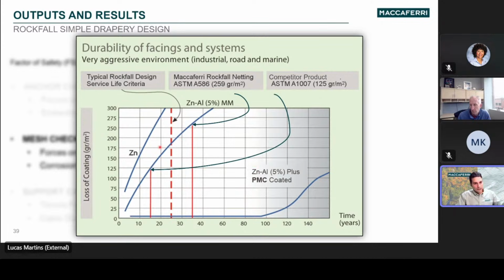But the amount of corrosion protection per unit area of the mesh is also important, because the way the corrosion protection works is it is losing its coating through time instead of losing steel. So that is also a key point here. So you can see that Maccaferri products can allow, because we have more steel in our products, a larger amount of galvanization. So once you have assessed correctly the aggressiveness of your environment, whether it's a very aggressive environment, a low aggressive environment, or a temporary application, you can correctly choose your coating requirement from that.